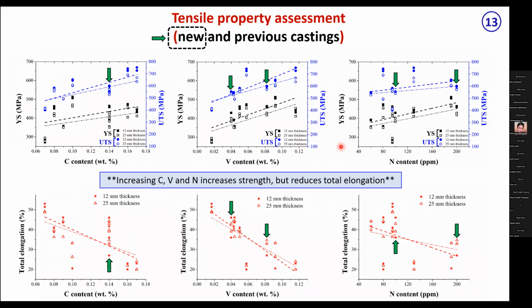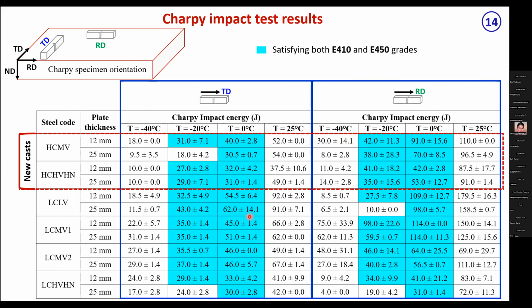So overall, we got the expected trend. These are the impact properties at plus 25, 0, minus 20, minus 40. Last time we presented impact properties only for the transverse sample, and we received a suggestion to perform impact testing on the longitudinal, rolling direction sample also. So this time for all the steels, we have done that. We can see the longitudinal results are much better, almost double in some cases, than the transverse properties.